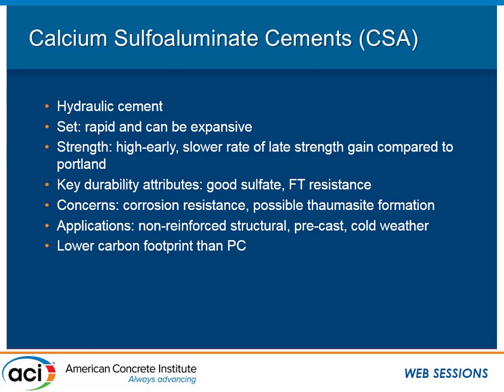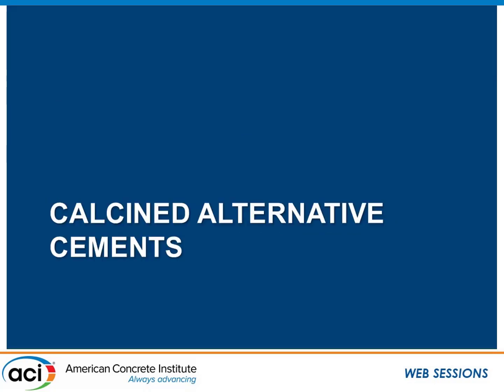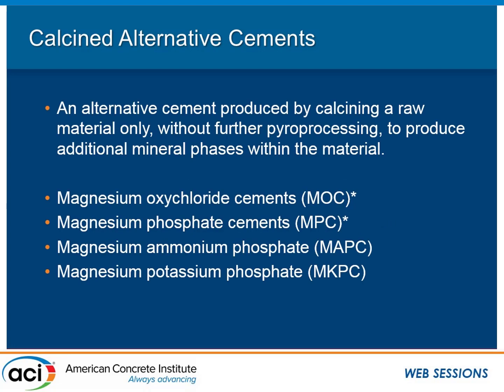So normal Portland cement has lots of A-lite, right? If you lower the clinkering temperature down, you would stop when you start to get the B-lite, and then the sulfoaluminate is added in to get a little bit higher early strength. So another good cement. Calcined alternative cements, we're looking at mostly magnesium-based